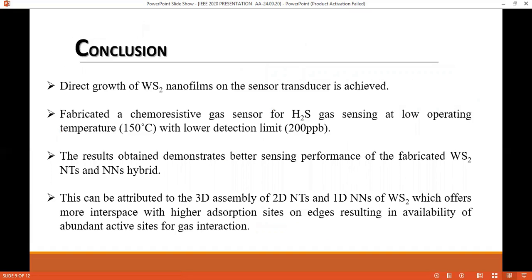Finally, to conclude, we have shown direct growth of tungsten disulfide nanofilms on the sensor transducer. Then we have fabricated a chemoresistive gas sensor for H2S gas sensing at low operating temperature with a lower detection limit of 200 ppb. The results obtained demonstrate better sensing performance of the fabricated tungsten disulfide nanotriangles and nanoneedles hybrid.